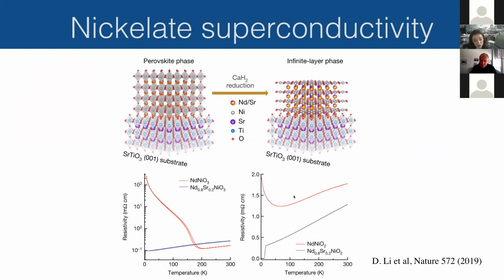There's also a large difference in the energy alignment between the nickel and the oxygen in the infinite layer nickelates, whereas in the cuprates they're much closer together, the copper and the oxygen. So there are several differences. There's a lot of theory papers already. And the paper here is not even a year old, but if you check on the archive, I'm sure there are like 50 papers at least trying to address the superconducting state of these guys. So it's definitely, like I say, ongoing work. There's a lot of mysteries here, and people are really trying now to understand it. Hopefully in a few years, we'll have a clearer idea of what's going on.